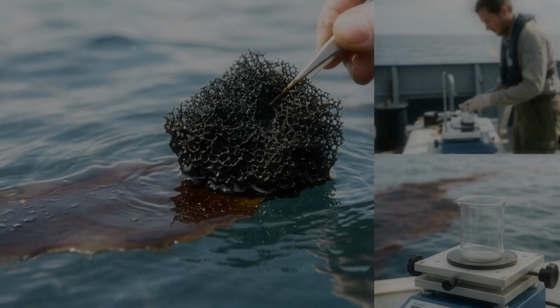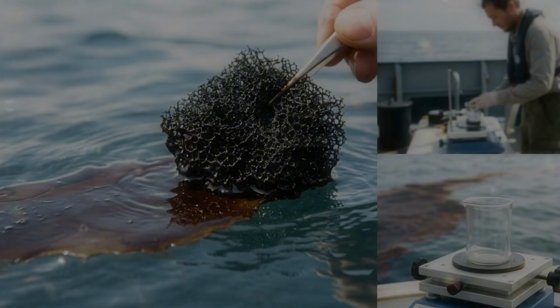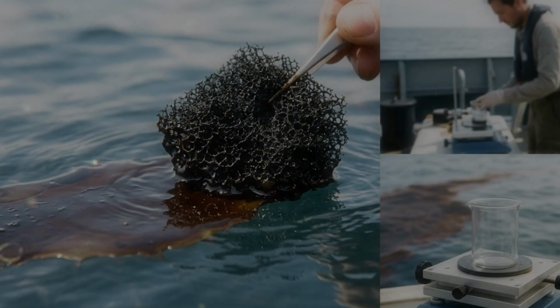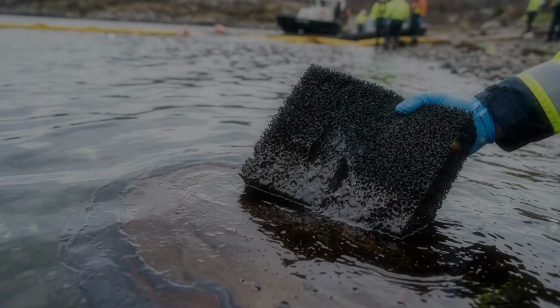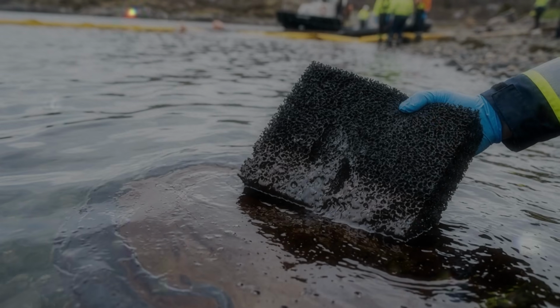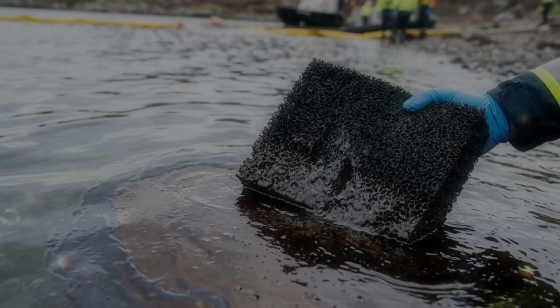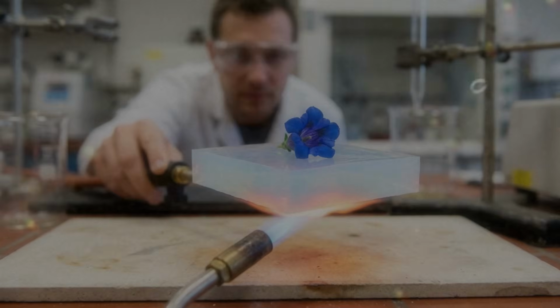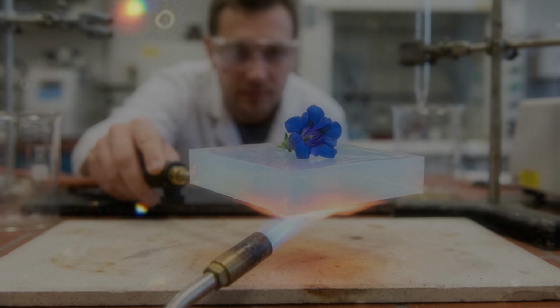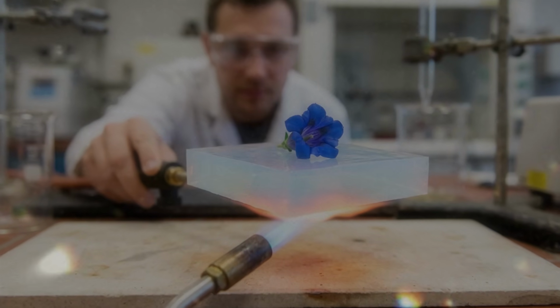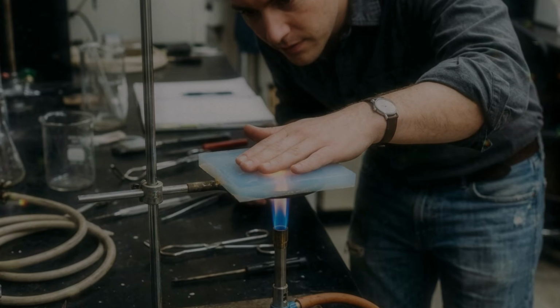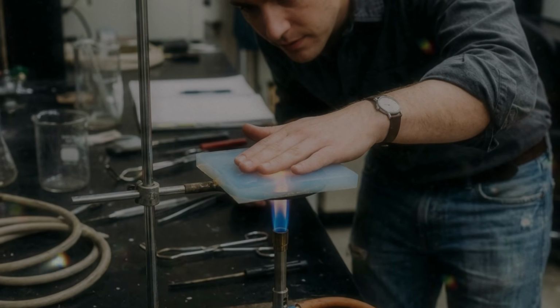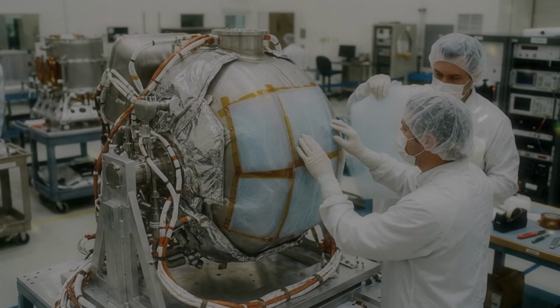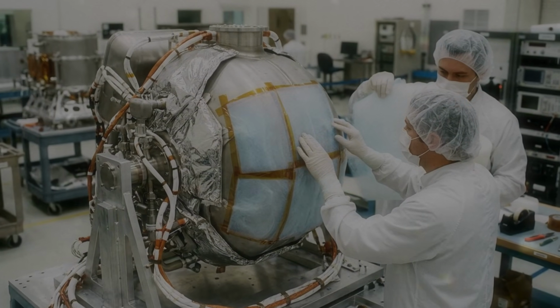A material with the lowest possible density may not have the best thermal insulation. A material with the greatest surface area may transport liquids too slowly. A highly conductive network may require more carbon and therefore more weight. Surface area is another result of the internal design. A large solid block has most of its atoms buried inside, away from contact with the outside world. In an aerogel, much of the solid exists as thin walls and small branches. A far larger fraction is exposed to the pores.